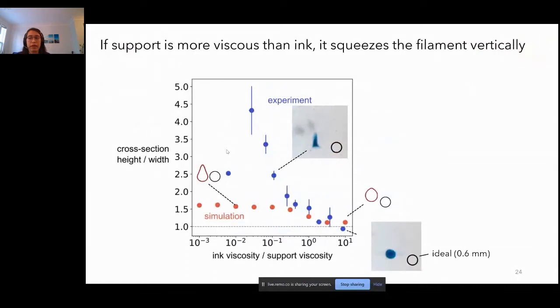So here, what you can see is that as you increase your viscosity ratio, you decrease the cross-section height over width. That occurs in both our simulations and our experiments. And there's pretty good agreement as we go to higher viscosity ratios. So what this tells us is that if the support is more viscous than the ink, it just ends up squeezing the filament vertically and creating these very tall and narrow aspect ratios. Another thing that we can note here is that you need to go to a viscosity ratio of greater than 1 in order to get a circular cross-section. So the ink needs to be a little bit more viscous than the support to get to this ideal circle.